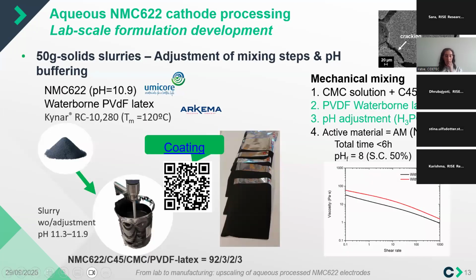On one of these waterborne binders with the example of NMC 622. In this case, it was still a PVDF waterborne latex, this fluorinated polymer that I was mentioning, using phosphoric acid as a pH buffer. The PVDF latex was from Arkema as a reference.